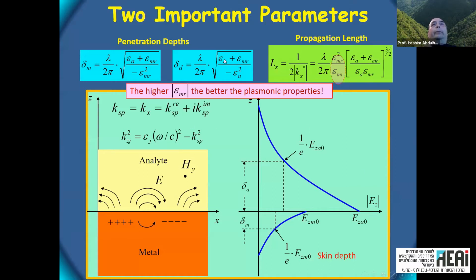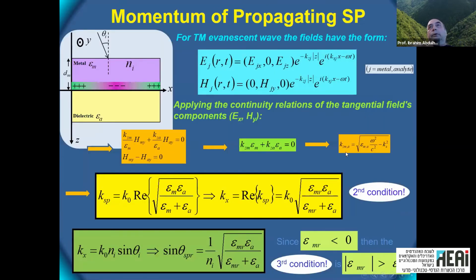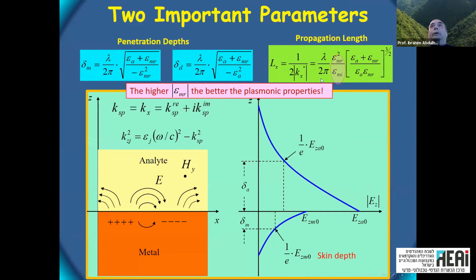Okay, so as mentioned, we do have the important parameter, which is called the penetration depth, and it is important for the sensitivity and selectivity. If we calculate Kz from here, we can know what the penetration depth will be, 1 over Kz basically. And we can easily find also the propagation length along X. Because of the absorption, as mentioned, Kx has an imaginary part. So 1 over the imaginary part will give the propagation length. If you want it in terms of the intensity, then we have a factor 2 here.